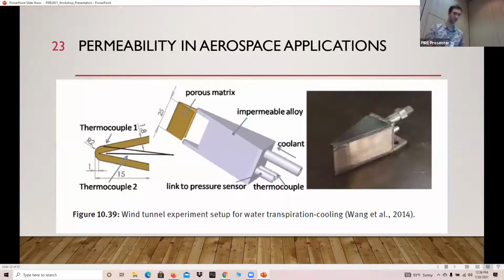And applications for these permeable systems, here's a paper from 2014 that is looking at exactly what we're looking to do. Hypersonic leading edges of vehicles need to be very, very sharp to allow for control surfaces without ablation, because as you ablate and it gets not as sharp, you lose more of that control of the fluid flow over the surface, so you need to keep it nice and sharp. However, the heat flux at those locations, where the radius of curvature can be less than 3 millimeters, which is really, really small, is wildly high, so you have to actively cool the surface because the operational temperature of silicon carbide composites is not adequate.